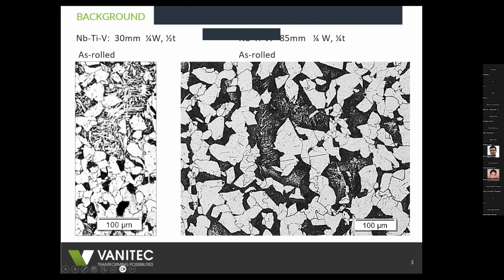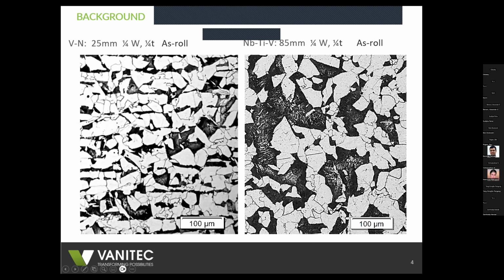So this is a recipe for disaster and gives you very, very poor toughness, well below the 27 joule criterion that is required. Now, contrary to this, you have vanadium steels with 25 millimeter plate, for example, on the left-hand side, and I'll deal with that in a little bit more detail in the following slide. You don't experience that very coarse structure as shown here, the repeated structure on the right-hand side.